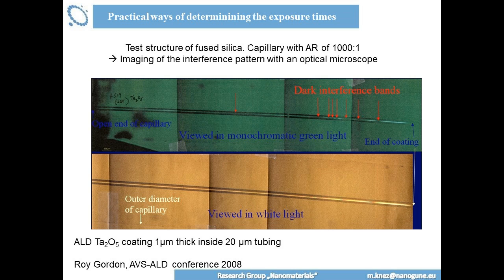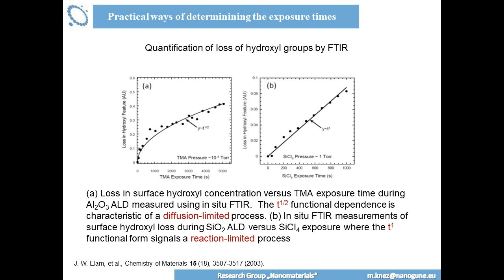So another point how to measure it, this was done by Gordon. It's quite old work. We showed this at the workshop in the early conference. You can coat capillaries and then take a look in the optical microscope. You have those interference bands which frequently occur. It's very easy then with the optical microscope. You don't need to go to TEM or SEM or whatever. You just look into visual phenomena with just the optical microscope to see how deep you could get into the pore. It's a bit unpractical, I would say, because you need to have very long capillaries. But okay, it's a methodology.